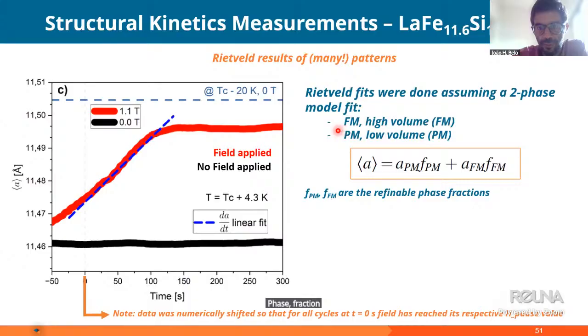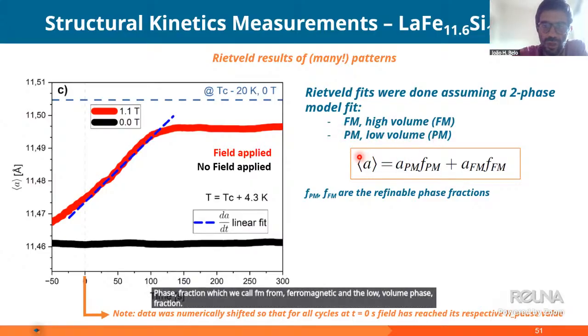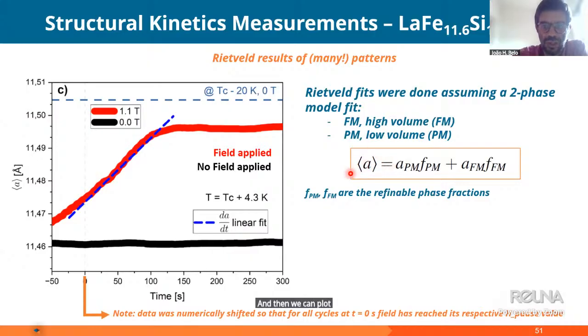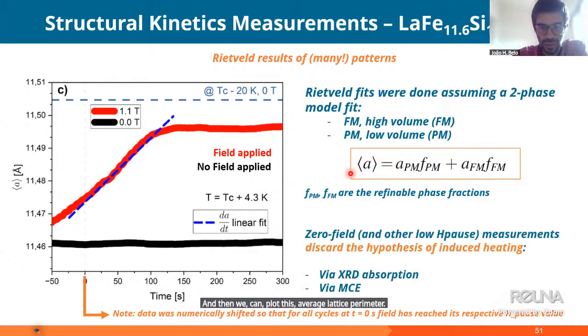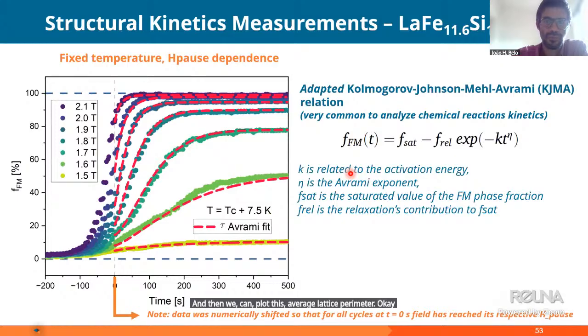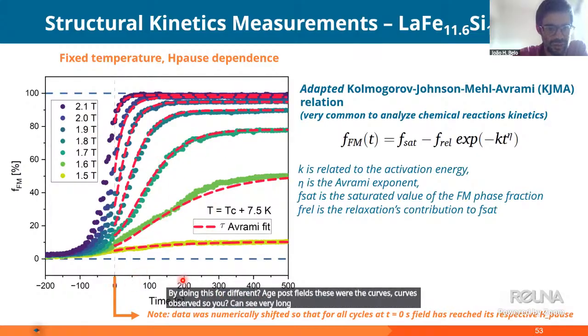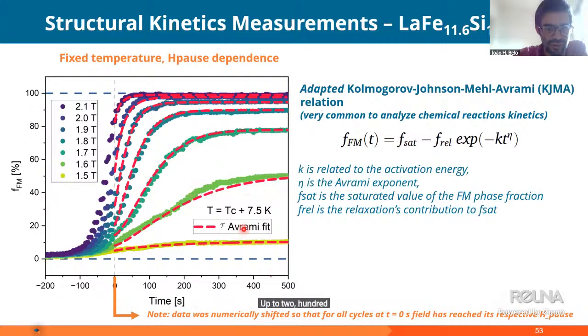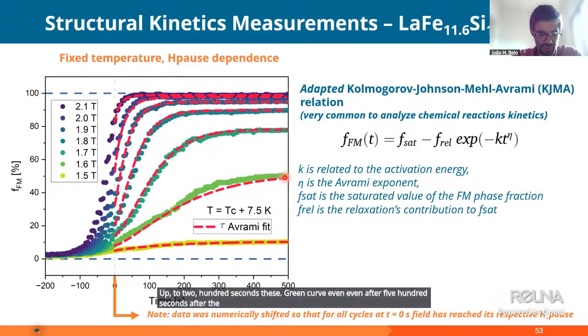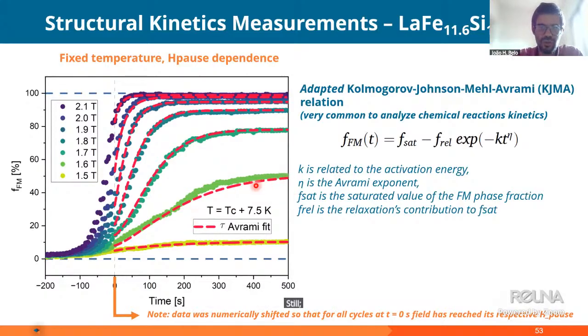And so by really knowing the lattice parameters, we could estimate the high volume phase fraction, which we call FM, from ferromagnetic, and the low volume phase fraction. And then we can plot this average lattice parameter. Okay, so by doing this for different H-pause fields, these were the curves observed. So you can see very long relaxations, up to 200 seconds. This green curve, even after 500 seconds after the field has been paused, is still evolving.